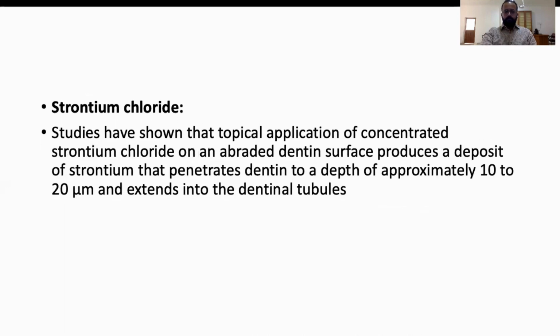Strontium chloride. Studies have also shown that topical application of concentrated strontium chloride on abraded dentine surfaces produces a deposit of strontium that penetrates dentine to a depth of 10 to 20 micrometers and extends onto the dentinal tubules.